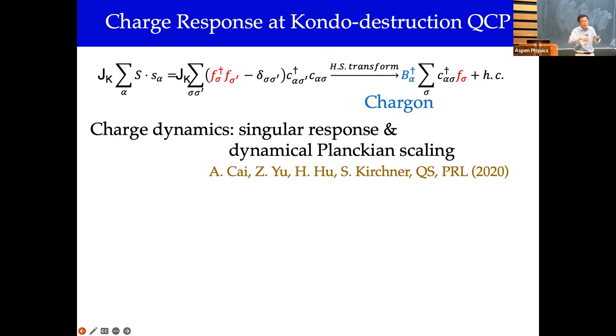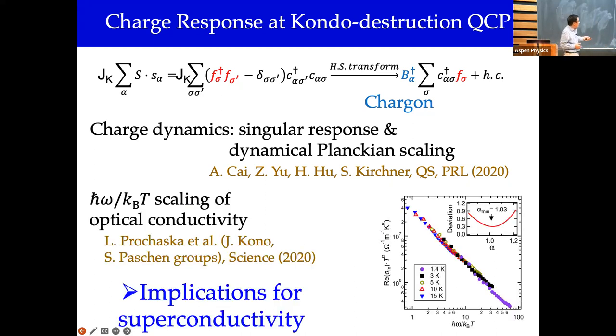And you can also think about this maximally entangled state of up-down minus down-up electrons. The electrons are involved. And so even though the spin degrees of freedom are forming the entanglement, the charge is also participating. We can work out microscopically that for this class of quantum critical point, not only is the magnetic sector quantum critical, but also the charge sector. And this is yet another set of measurements done using the MBE films of the Vienna group. This is my colleague, John Kono, who did terahertz measurements. You show that the charge sector also has this Planckian-like ħω over k_BT scaling in this terahertz optical conductivity.